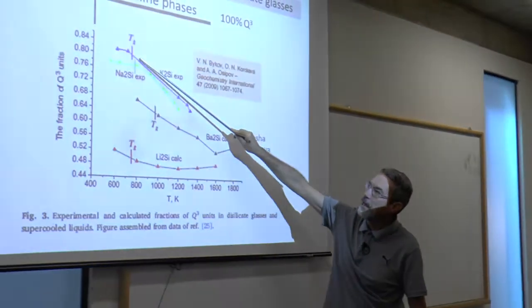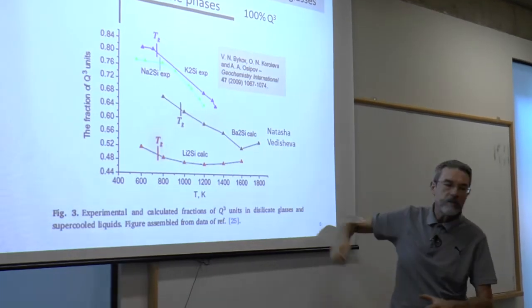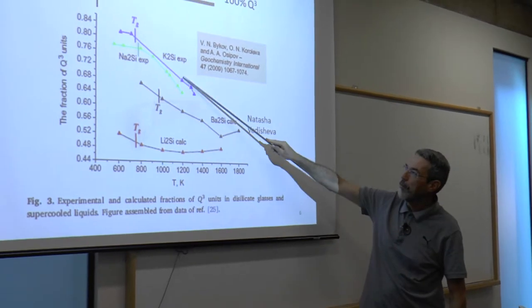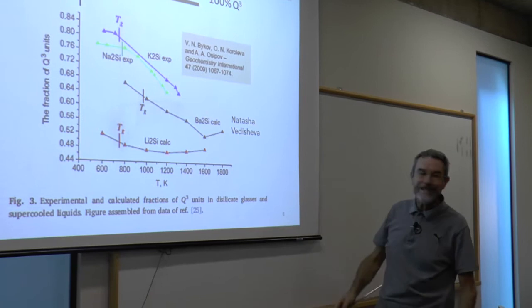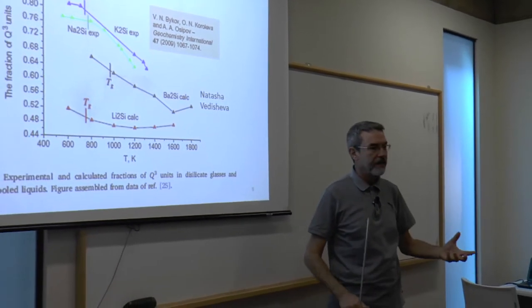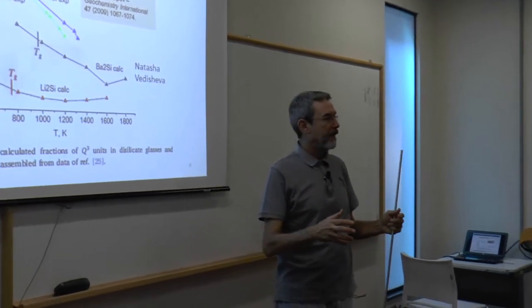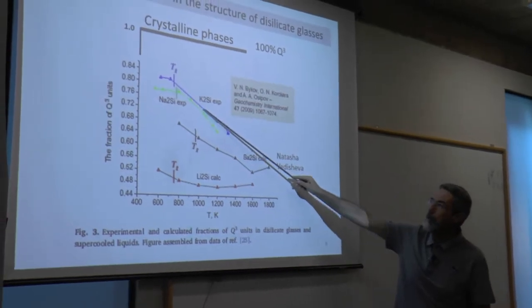Okay? I like this plot very much because it conveys the idea that the structure of the glass is just the same as the structure of its supercooled liquid a few degrees above Tg. Of course, if we heat the supercooled liquid a lot, we start to depolymerize this structure more and more. This is the equivalent of the degree of polymerization in the polymer. If you have a Q4, like pure silica glass is Q4, all the tetrahedra are sharing the four corners, highly polymerized. When we add sodium or lithium or calcium or anything, we break bonds and start to depolymerize the structure, and also the temperature has a similar effect.